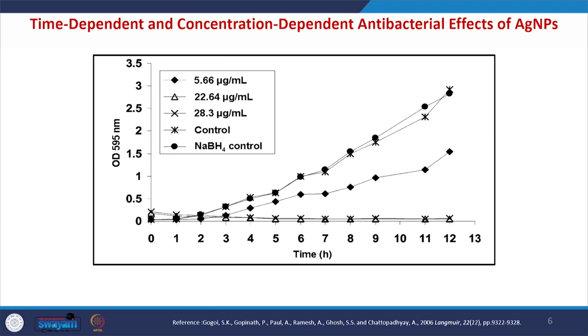And we can also do the time dependent study to understand at what time point the nanomaterial is killing the bacteria, and in this case we used a silver nanoparticle, and the silver nanoparticle is made using sodium borohydride as a reducing agent. So, to confirm that the bacterial death is due to silver nanoparticle and not due to the reducing agent, we have to use sodium borohydride as another control.